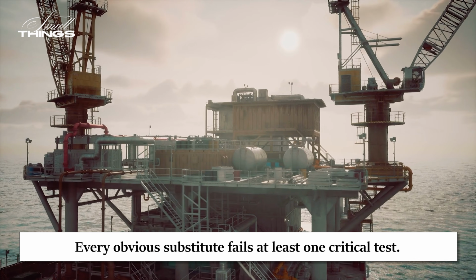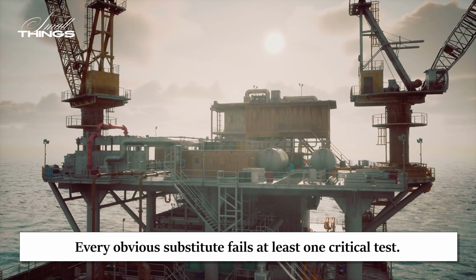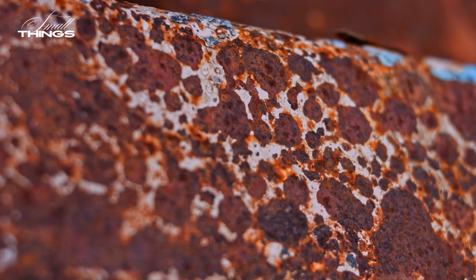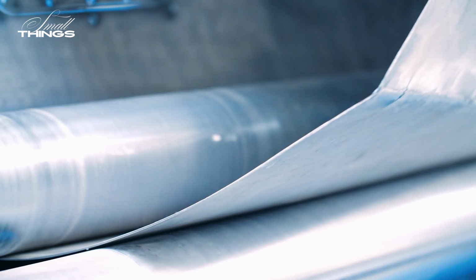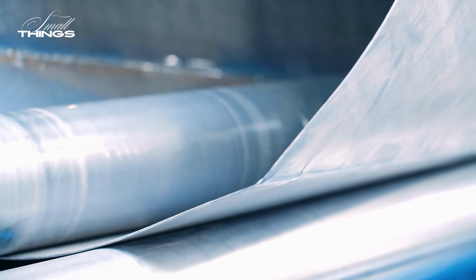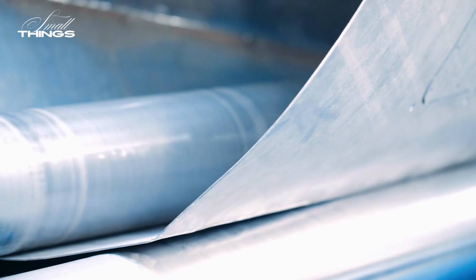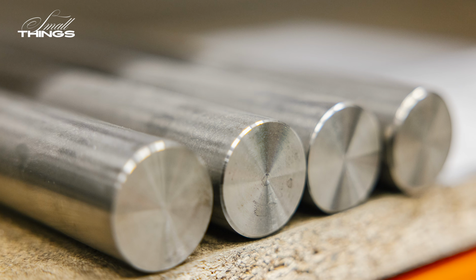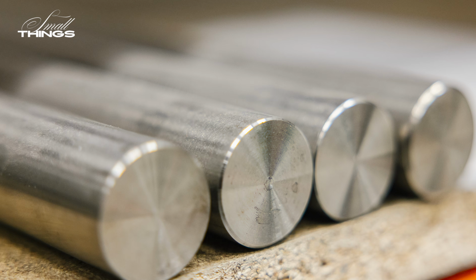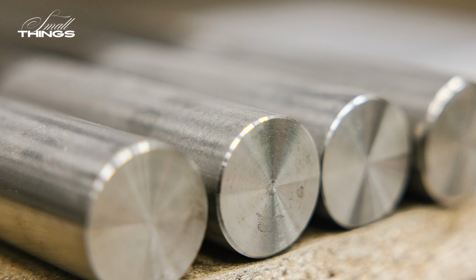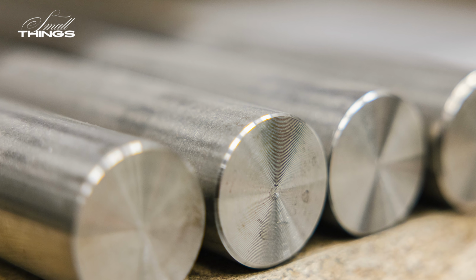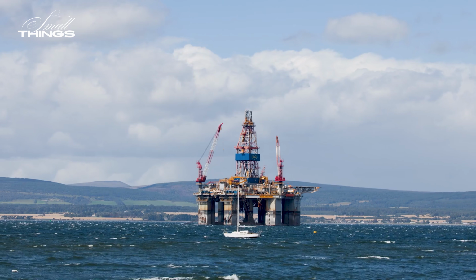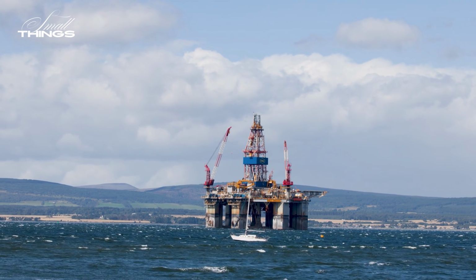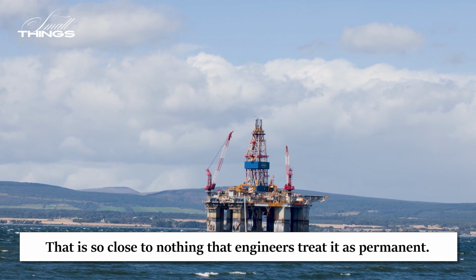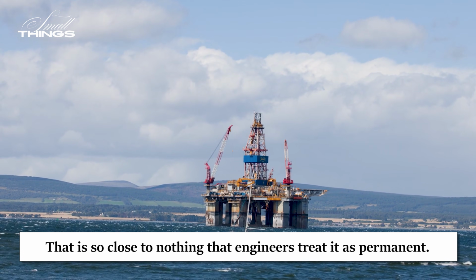Every obvious substitute fails at least one critical test. Standard steel rusts. Stainless steel can crack silently under the combined pressure of mechanical load and chloride ions in flowing seawater. The component looks completely fine until it does not. Monel does not crack. In flowing seawater, it corrodes at roughly 0.0025 millimeters per year. That is so close to nothing that engineers treat it as permanent.